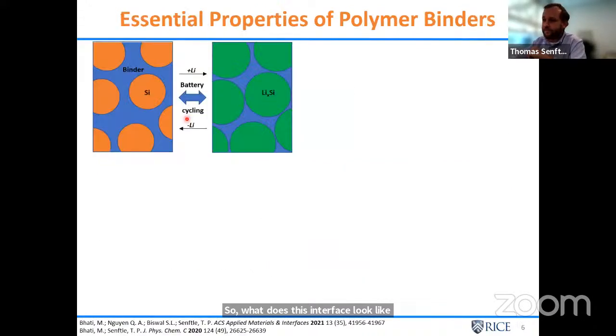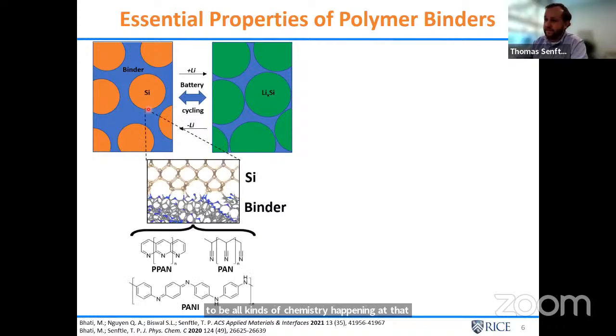That's the key question. So we have our binder, we have our silicon, and if we just look at the cartoon form, we know the silicon is going to expand when we lithiate. It's going to expand into the binder, and there's going to be all kinds of chemistry happening at that interface, right? So if we zoom into that interface, we have our silicon material, we have our polymer binder. There's specific bonds that are forming at that interface that really are going to control the behavior of the electrode. And this is where the atomistic simulation comes in. We want to go from this sort of macroscopic picture to the microscopic picture so we can understand how we can design the binders at the molecular level to optimize performance to really stabilize this interface.